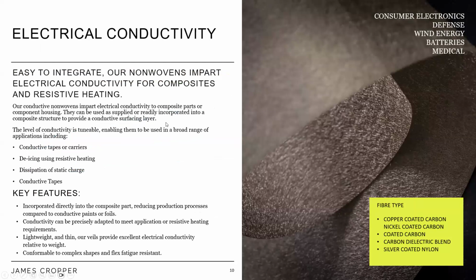As we discussed, coating a minimal amount of metal onto the surface of the carbon fibers can enhance the conductivity of the nonwoven by about an order of magnitude or more. And the metal coated carbon nonwovens are a great choice if conductivity of the composite part needs to be enhanced. The level of conductivity can be tuned by varying the weight of the nonwoven, which is a massive benefit. There are also applications that benefit from a slightly more resistive material, such as resistive heating. And the inherent conductivity of the carbon fiber provides an excellent platform to manufacture materials with higher resistance values.